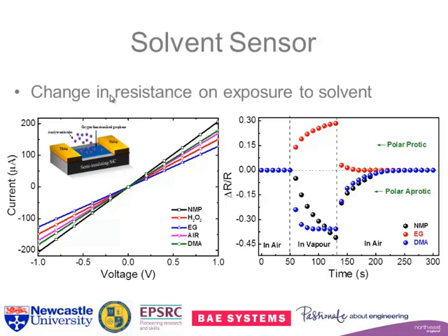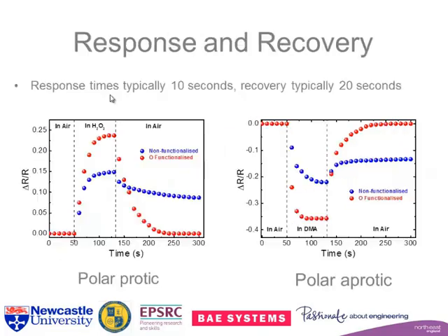And then here on this side, we see the same thing. These are polar aprotic, so they're polar materials, but they don't have a hydrogen donating ability. Note here that in 75 or 80 seconds, we've got saturation for 2 of these. NMP hasn't. We also get recovery. This is something that a lot of graphene-based sensors do not get.